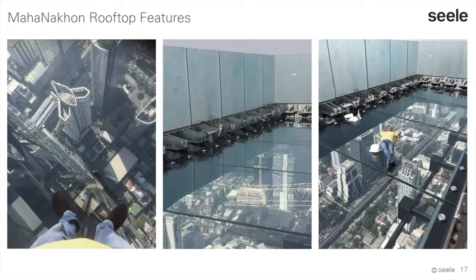What you can see there along the edge of the glass, this is Seele's so-called glass retention system. It's a special point fixing technology which fixes the glass in the bracketry in order to avoid that in case of a complete glass failure, a complete glass breakage, the glass can slip out of its bracket and fall down with all the people on it. So this would not happen. So even if you have a complete failure of glass and people, the glass full with people standing there, the glass would not slip out, would not fall down. It's absolutely safe. It would just sag down 2-3 centimeters and then stop, and that's it. And all the people can leave the roof safely.